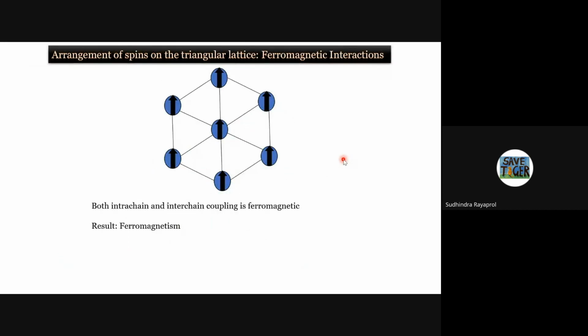And when you have a hexagonal lattice, you can have a triangular arrangement of the lattices also. So when you have this kind of arrangement, you have two chains with a third chain with a different cation at different positions, you can have different kinds of geometrically frustrated ground states. Now in this example, if all the chains are coupled ferromagnetically, then the interchain coupling is also ferromagnetic. So the end result will be a ferromagnetic ground state.